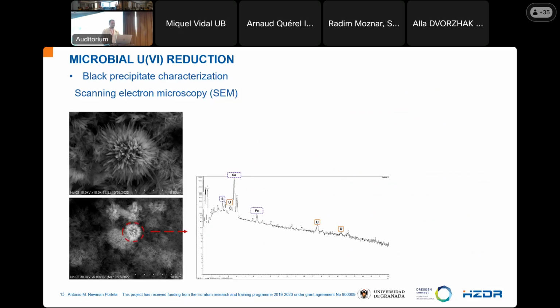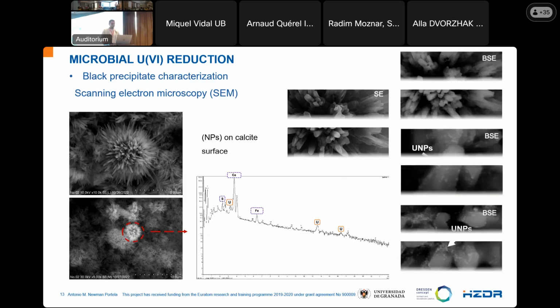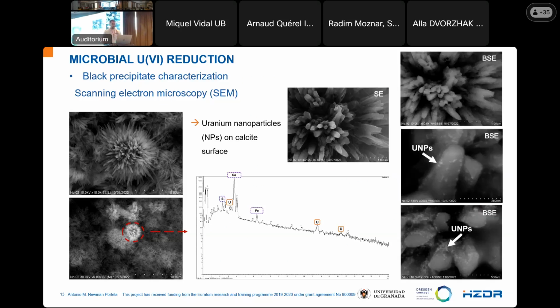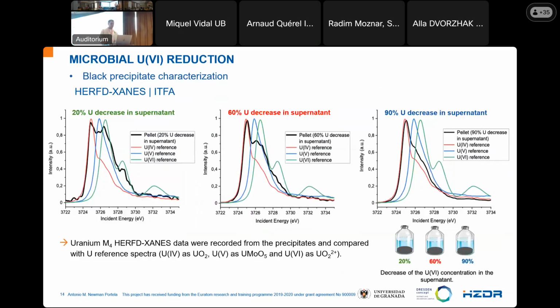When we analyze this calcite structure by EDX, we identify uranium on them. And thanks to the backscattering electron detector, we identify possible uraninite nanoparticles on the surface of the calcite structure. Okay, to get more detailed information about the black precipitate, we use HERFD-XANES and EXAFS measurements.